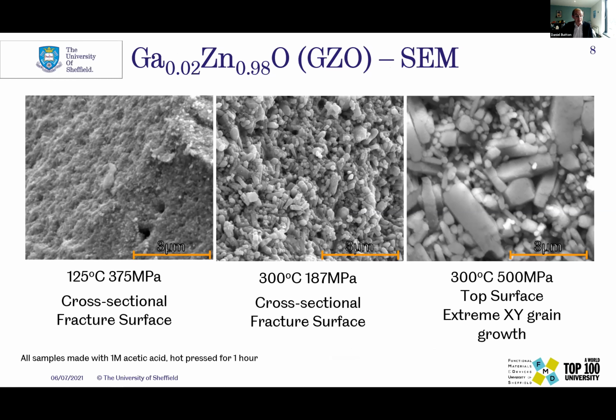It did need a slightly higher temperature than the normal cold sinter stuff. You can see on the far left, basically there was almost no densification that took place at 125 centigrade, which would show a bit of densification with cold sintering usually. This is expected, however, as the introduction of the gallium oxide, which incorporates itself into the grain structure, is well known to inhibit grain growth and densification, even in conventional processes.